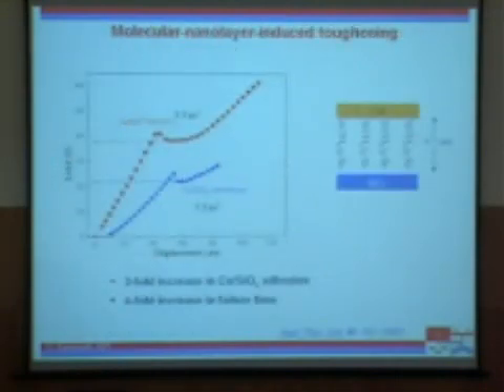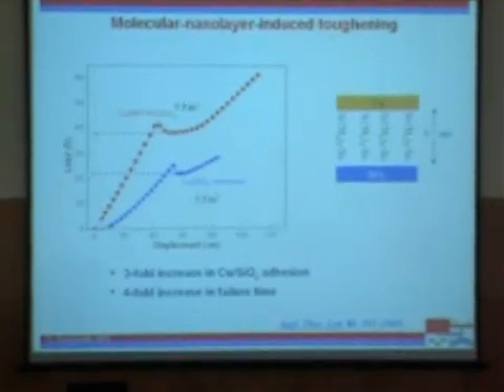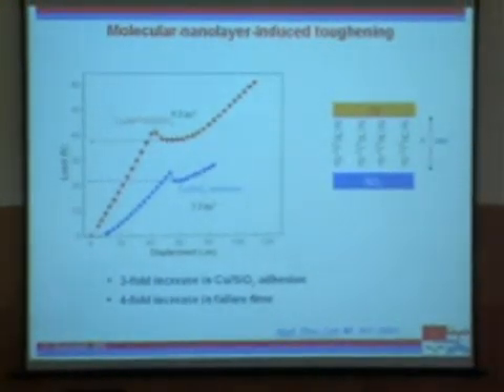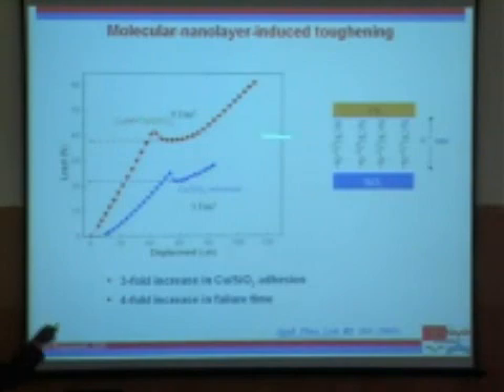In fact, very few places in the world have this machine. We built it ourselves. We didn't invent this technique, and Intel actually uses this as a benchmark. So you have load versus displacement for a copper silica interface without anything, and the toughness value that you get is 3 joules per meter squared. I'll tell you what this means in a minute. Once I put a molecular layer with a sulfur group on top, and a propyl group in between, you get 9 joules per meter squared. Again, unoptimized, and we have triple the toughness value.